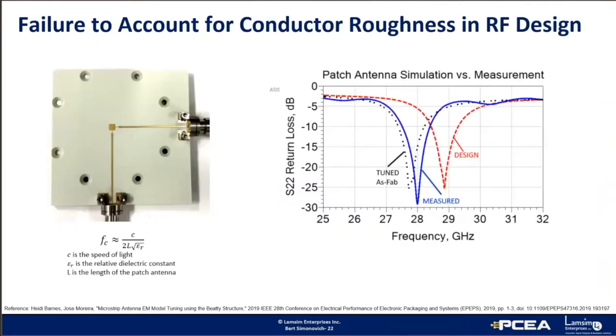And then there's the failure to account for conductor roughness in RF design. Here's an example from a paper by Heidi Barnes and Jose Moreira, and it shows the red plot is the simulated result of an antenna resonant frequency when the roughness of the copper was not considered in the simulation. When they corrected the effective Dk due to the roughness, the simulated frequency was much closer to the measurement.